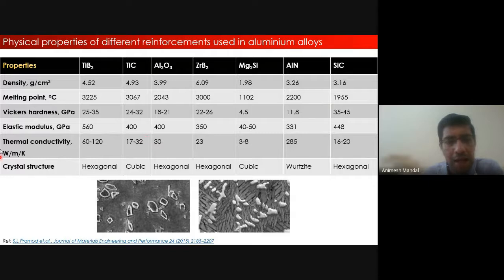Now, if you have a look at these properties, you can see they're relatively denser than aluminum. Aluminum density being 2.7, only magnesium is lighter, but more or less the others are quite denser. All of them have a relatively high melting point, and the Vickers hardness is quite high. Of course, they are ceramics. The elastic modulus of all these is pretty high, except for, say, Mg2Si. The thermal conductivity is on a lower side.